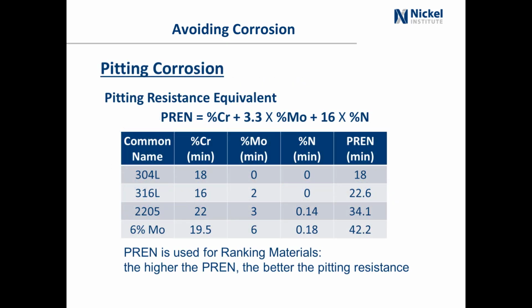You can rank the various stainless steels with regards to their resistance to pitting corrosion by a formula called the PREN, which looks at the chromium content and the molybdenum content and the nitrogen content. And here are the same 4 stainless steels that I had showed previously. And 304, since it only has chromium in it, has a PREN of 18. 316, which has both chrome and molybdenum, its minimum PREN based on that composition is 22.6. 2205 is 34.1, and a 6 moly stainless steel is about 42 as a PREN number.